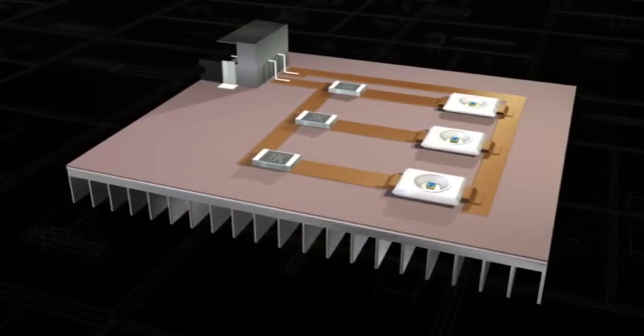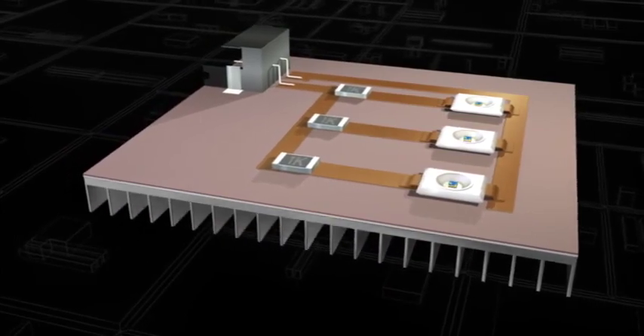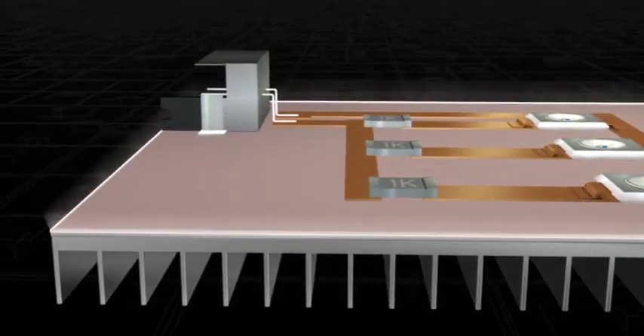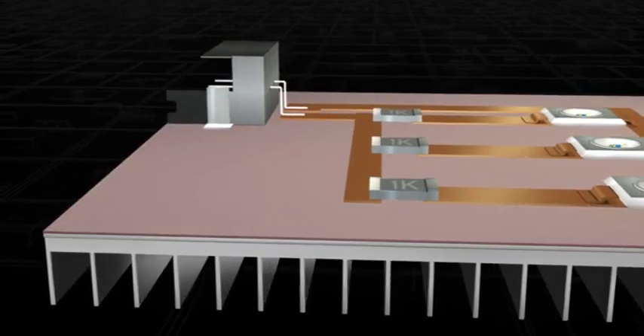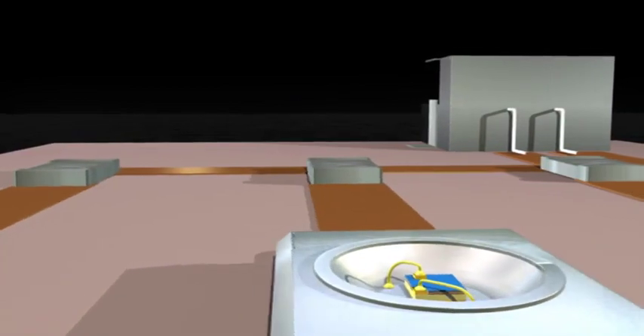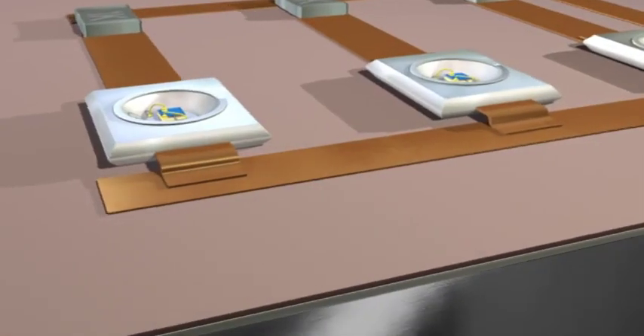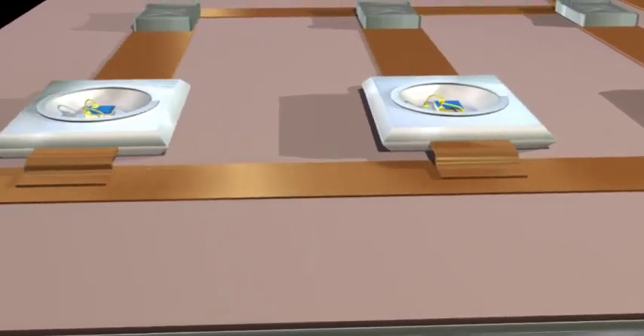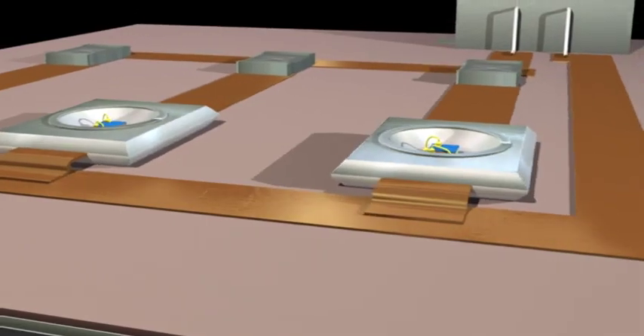A major advantage that OPTEK offers in heat management is its OPTOTHERM substrate. OPTOTHERM is a proprietary substrate that utilizes a copper-clad circuit that is bonded to a thermally conductive dielectric material. This is then bonded to an aluminum substructure. This combination exhibits very good thermal characteristics and serves as the initial step in getting heat out of and away from the packaged chip. OPTOTHERM reduces thermal resistance to an extraordinary 1.8 degrees centigrade per watt, well beyond competitive products. Breakdown dielectric is an impressive 4,000 volts.